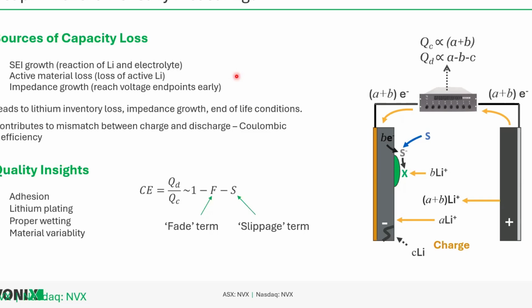We count what's happening. So there's a couple contributions to counting electrons moving through these circuits and how they differ from charge discharge throughout cycling a cell. So one is when we lose capacity. This can be SEI growth, active material loss, etc. Every cycle we'll be losing lithium inventory to certain reactions or mechanisms within the cell. And then every subsequent cycle will count fewer electrons. The more accurately we can do this, the quicker we can detect very subtle changes happening in a cell.